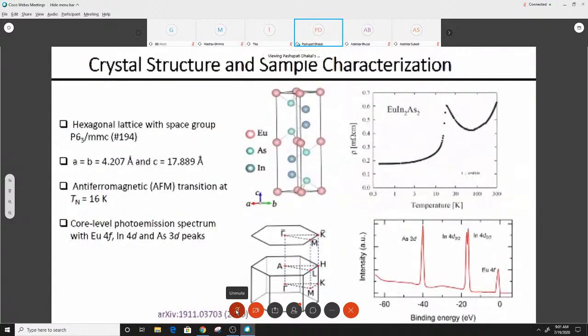And the material we found was EuIn2As2. It crystallizes in space group 194 with a hexagonal lattice. The lattice parameters are as shown. Very large c compared to the in-plane parameters makes the 001 surface a natural cleaving surface. So on this figure, we show the 001 surface Brillouin zone as well as the bulk Brillouin zone. On the resistivity measurement shown here, we can see a sharp peak at the antiferromagnetic transition, 16 Kelvin. And on the core level spectrum, we can see clear peaks of Eu 4f and As 3d, showing the good quality of our samples.